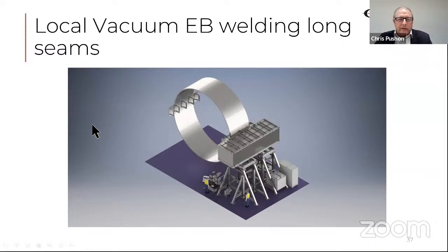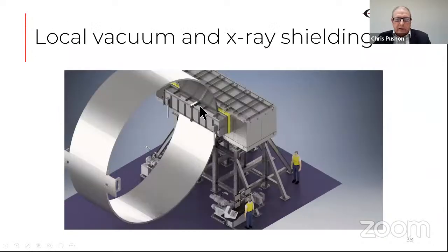So moving forwards, one of the issues you could probably see is that you have to put the component in an X-ray shield to protect the operators from ionizing radiation. What the engineers at CVE have done now is produce a system with a local X-ray shield, which means the operators can sit here quite happily. If they need to be there, they don't actually need to be there anymore because it's a digital process, and they can carry out these long seams without a big chamber. So it means you can put very big structures into the system. So here you see the localized shields just around the corner here.